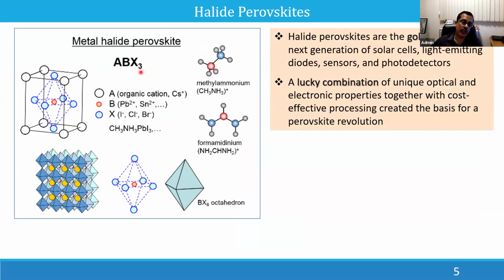X anion. Instead of oxide anion, they started using halide anions, iodide or chloride or bromide, and they found that it became much easier to make this material. Actually, these ABO3 materials are not so easy. They are very strong, and you need high temperature to work on those materials to make them into some other form, or to make films or crystals. If you want to synthesize in the laboratory, you need to use 500 or 700 degrees Celsius ovens, and that is not an easy process, and that will obviously increase the cost of fabrication. So people started working on this structure because it is very interesting,